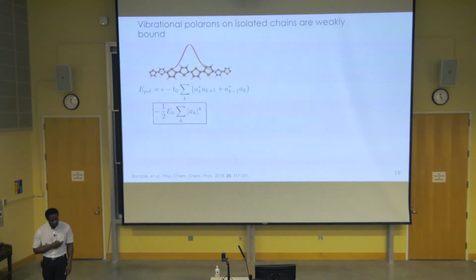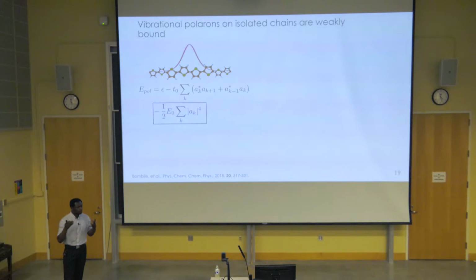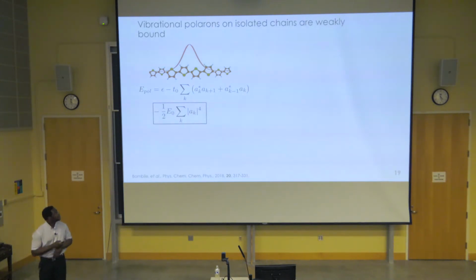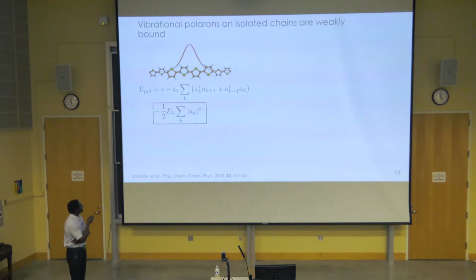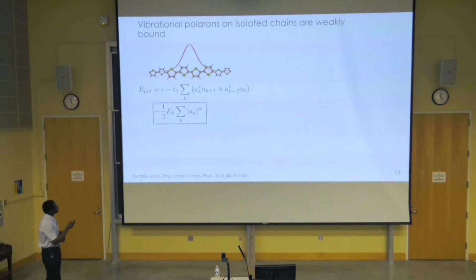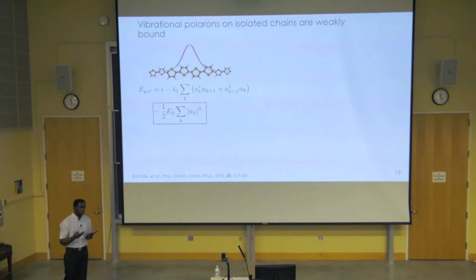Quickly, for polarons in one-dimensional chains with the ions or nuclei reorganizing, we have two terms that are part of the polaron formation. The first one is the energy of the charge carrier that we were able to represent with our tight binding model. And here, these A are the amplitude of the wave function on a given site. And the second term here is the stabilization energy that comes from the reorganization of the nuclei within the chain around the charge carrier.